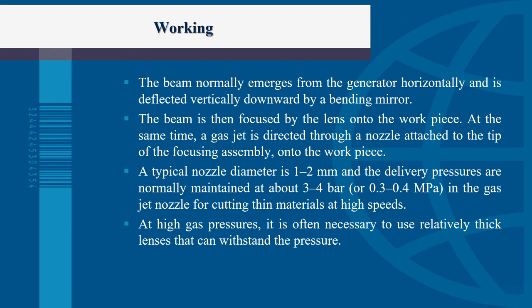So the beam normally emerges from the generator horizontally, meaning the direction would be similar to this as we saw in the previous picture, and then it will be deflected vertically downwards by a bending mirror. The beam is then focused by the lens onto the workpiece, and at the same time a gas jet is directed through a nozzle attached to the tip of the focusing assembly onto the workpiece. A typical nozzle diameter is about 1 to 2 millimeters, and the delivery pressures are normally maintained at about 3 to 4 bars, or 0.3 to 0.4 megapascal, in the gas jet nozzle for cutting thin materials at high speeds. At high gas pressures, it is often necessary to use a relatively thick lens that can withstand the pressure of the gas.